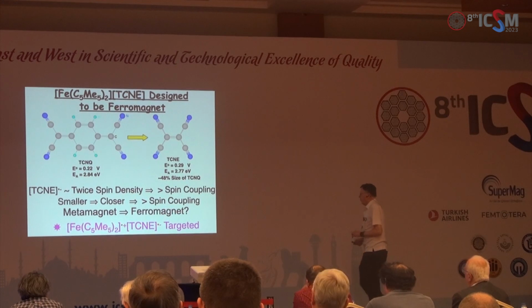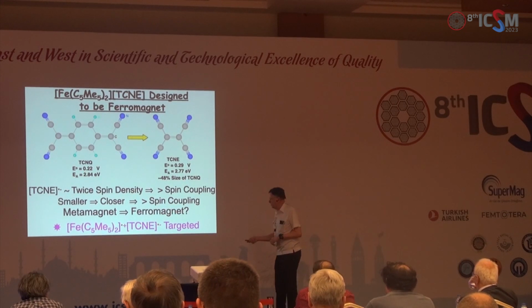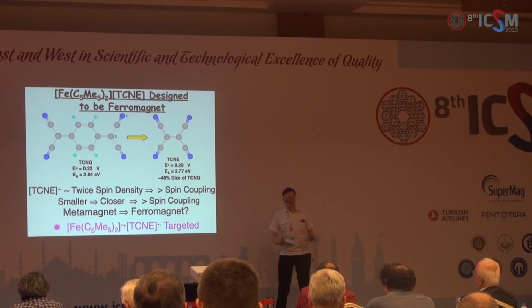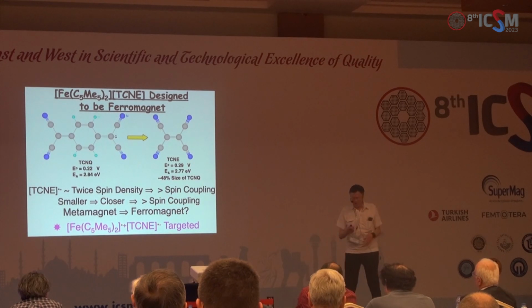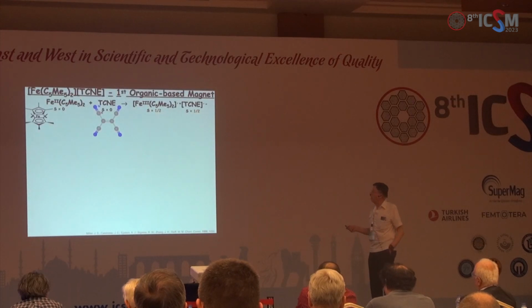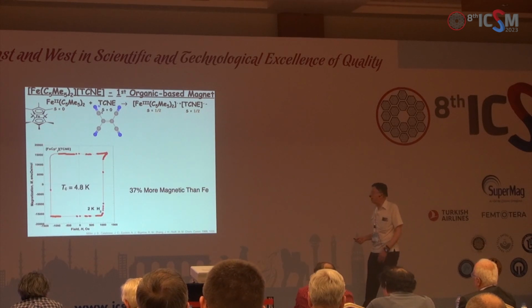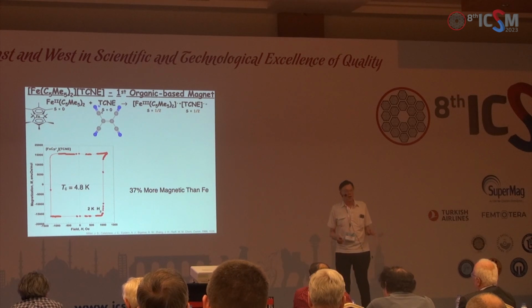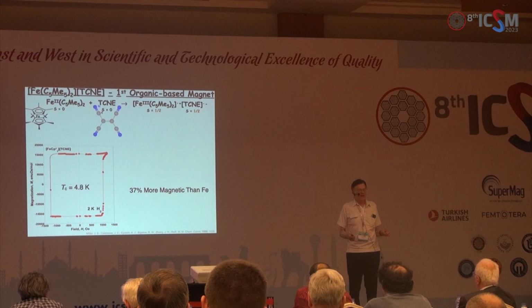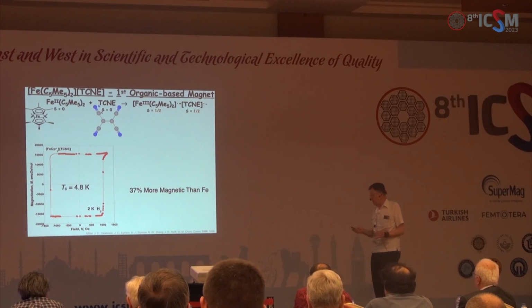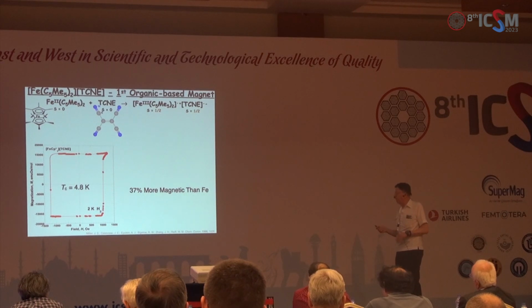And so we proposed the synthesis of decamethylferrocene TCNE. We targeted it, went into the lab, and it was painful to make—I won't go through that. But the fact is it oxidizes iron 2 to iron 3, which picks up a spin, and the TCNE is reduced to the radical anion, which also picks up a spin. We'll talk about the structure later, but I'll simply tell you that at 4.8 Kelvin, it magnetically orders as a bulk three-dimensional ferromagnet. Here is some data—we have a lot more than this—for it.